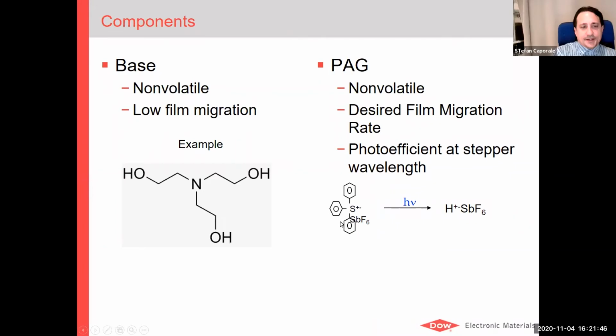So your benzene rings here, your group's absorbing all the light. It has to be optimized for that stepper. The more energy it takes to break your PAG apart, the longer it needs to be on the stepper, and that costs money. Because again, if you're printing 50,000 chips on a single wafer, normally we see those, it's scanning across and wants to do those in less than a second a piece, because every wafer wants to be on the stepper for a minute or two.